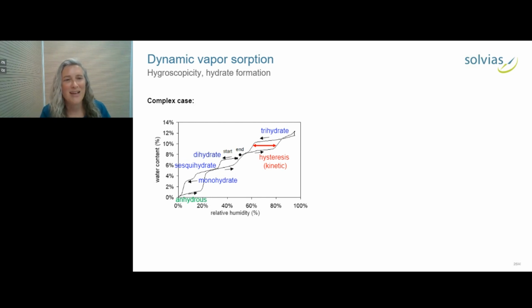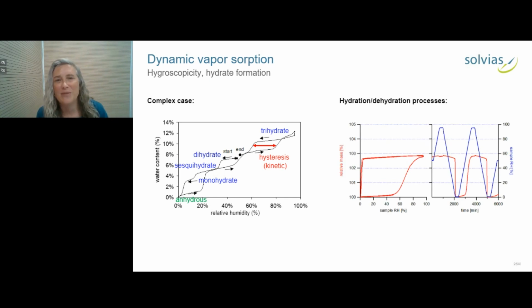Now, as you can imagine, such a complex diagram, it would have been a nightmare to try to develop just one of these forms. And this led the customer to do a salt screening, and we successfully found a new salt that was not so complex. Here on the right-hand side, you might see a more typical hydration-dehydration process. Here, what you have is a monohydrate form. And if you look at the blue curve, that's the humidity ramping.